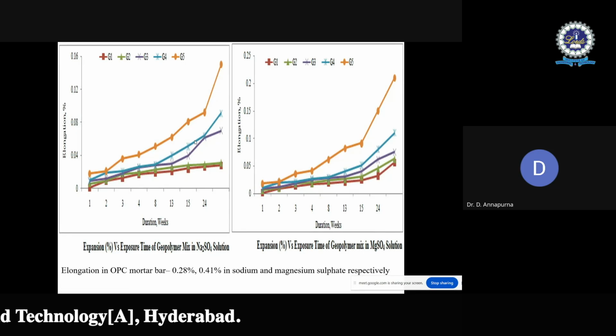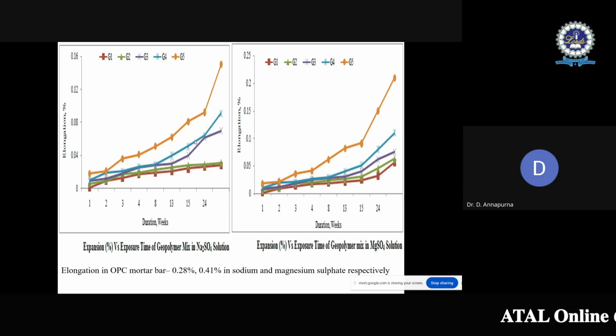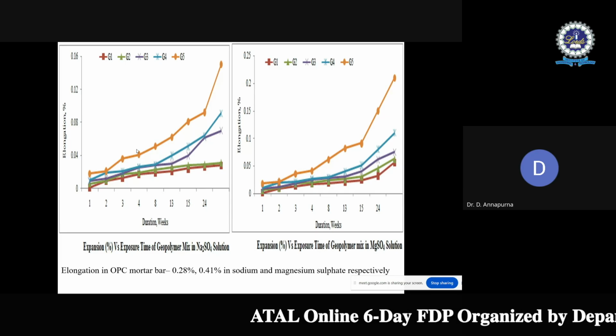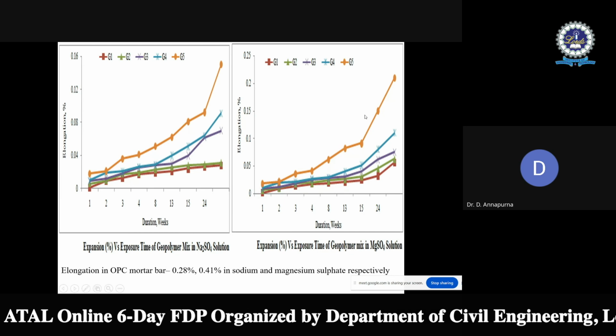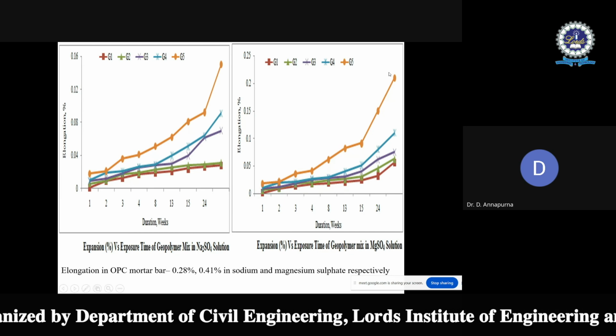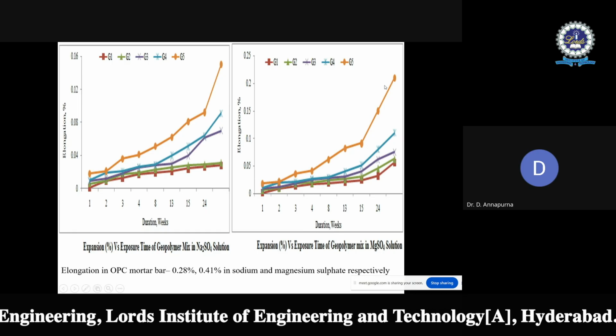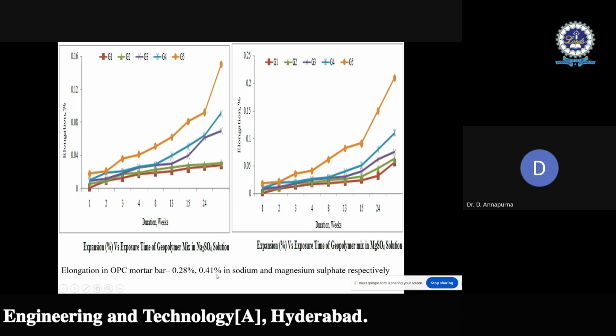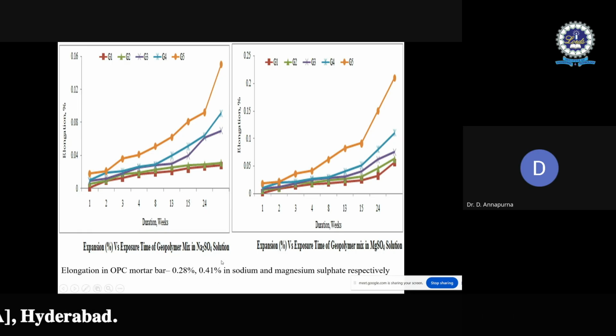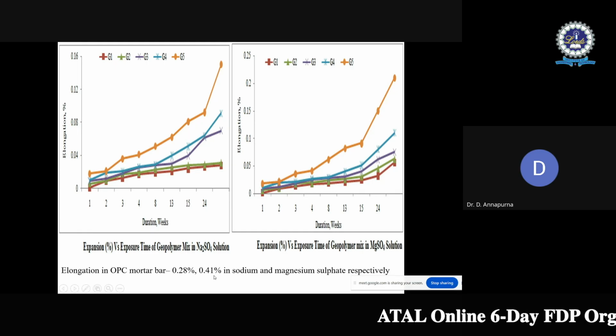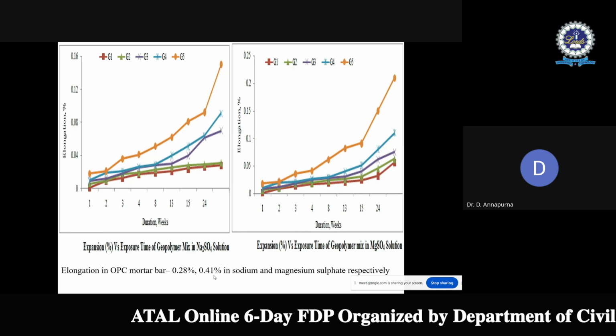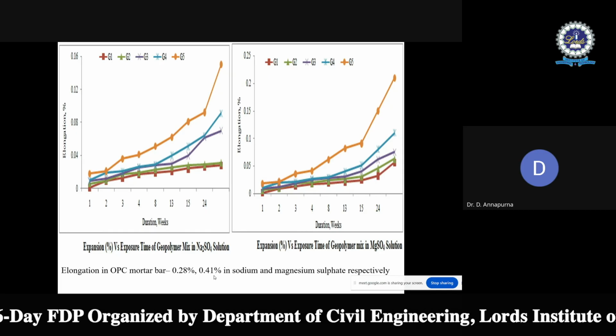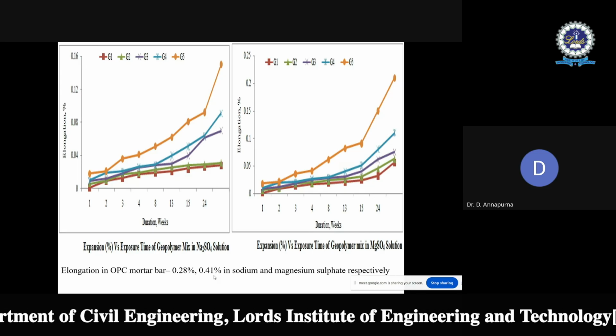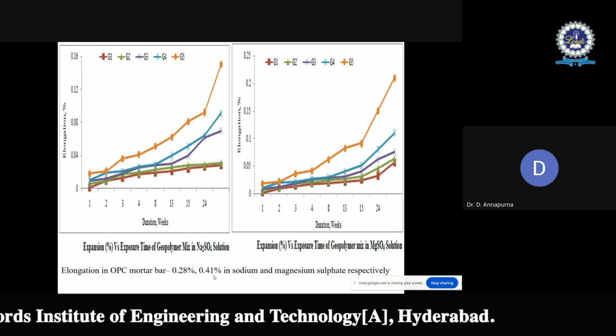Percentage elongation is also increasing, from 0.031 to 0.15%. The maximum increase is seen when the samples are immersed in magnesium sulfate. But when compared with the ordinary Portland cement based mortar, higher expansions are seen, 0.28% and 0.41%. So again we can say there is better resistance capability of the proposed geopolymer concrete in the sulfate solution compared with the ordinary Portland cement mortar bars.